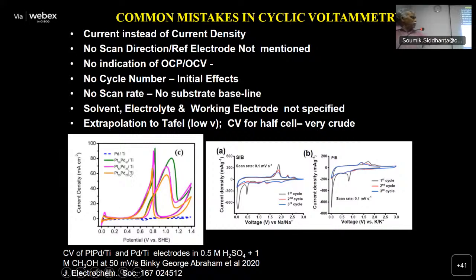Look at this. This is important because of methanol oxidation. You see a forward peak, coming back, and a reverse peak happening. The reverse peak is actually due to poisoning of the catalyst. Platinum, palladium, ruthenium: you will see methanol oxidation. You will see forward, go back, come back, and then there is a reverse. So the forward by reverse or reverse by forward ratio will allow you to quantitatively express the extent of poisoning. That's why this technique is important.